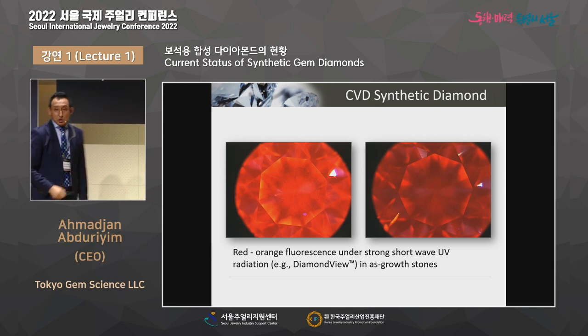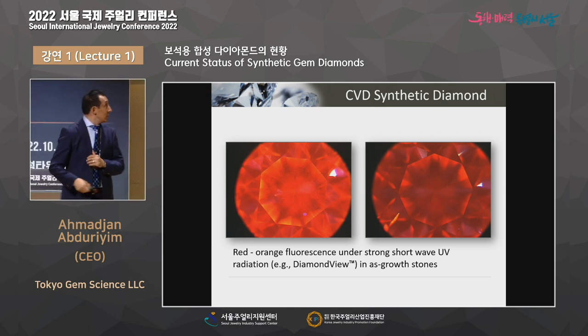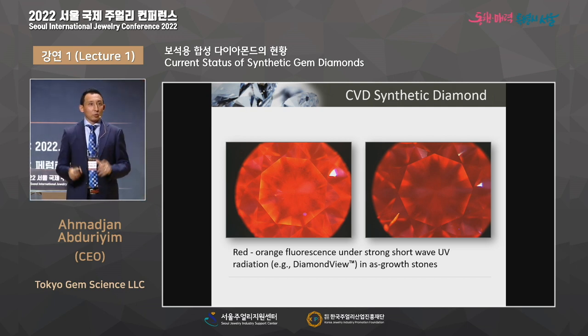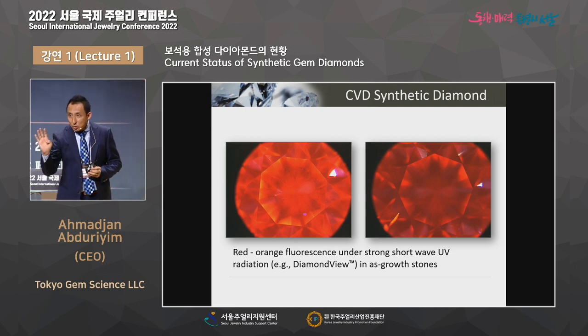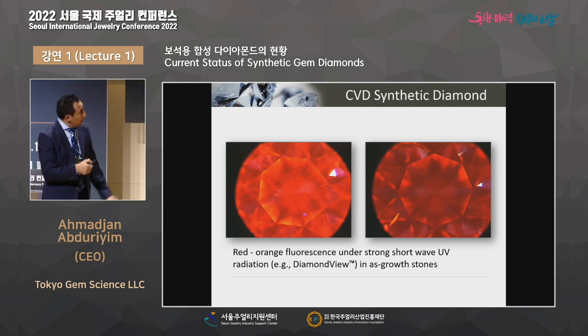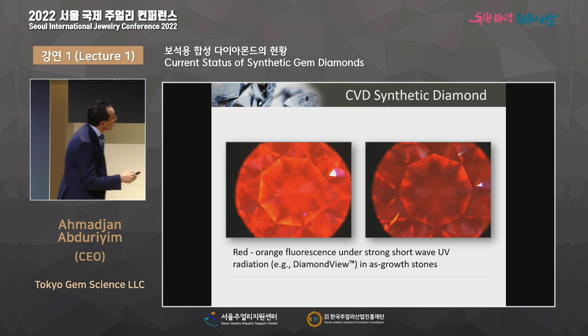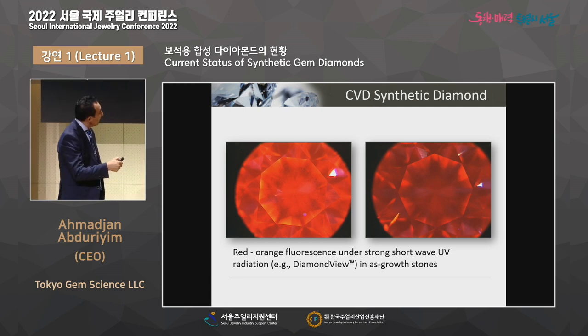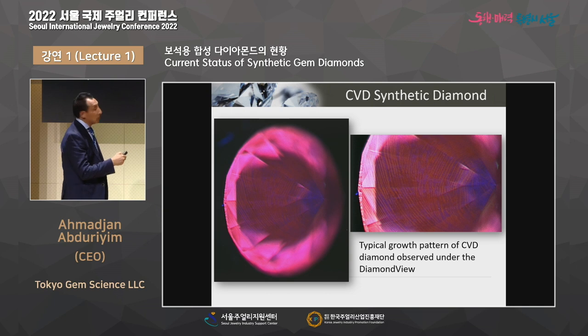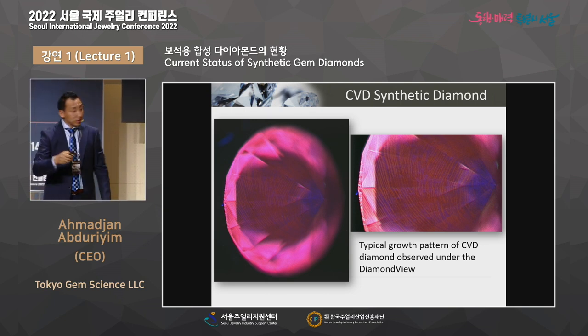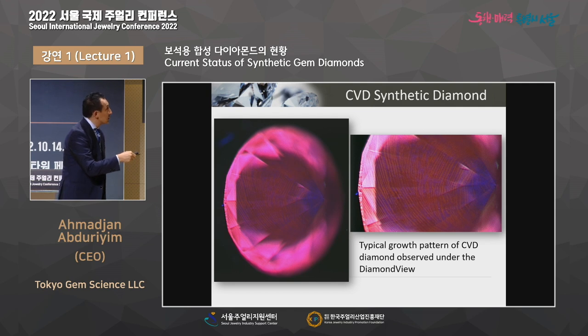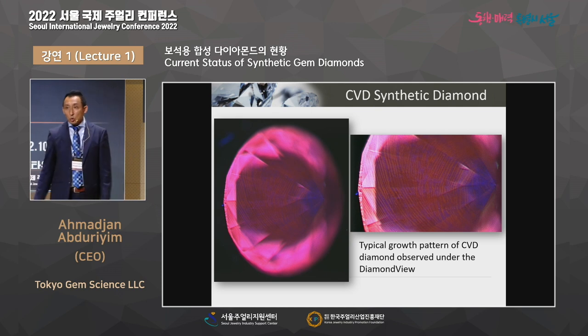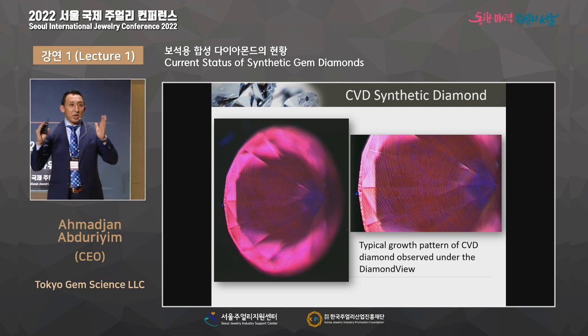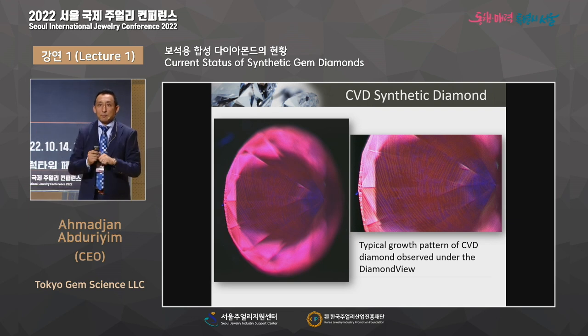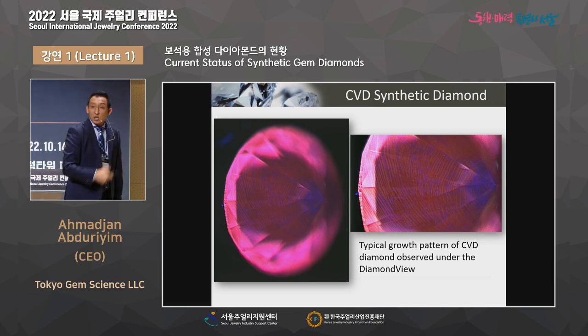You see, they show very strong red fluorescence. You never see such strong red fluorescence; Argyle pink diamonds show a little bit weaker than this. And here we try to see the very tiny growth structure. It's difficult to see. From the side view, you see layer by layer. This is definitely a CVD diamond. You never see this structure in natural diamond. You never see this structure in HPHT synthetic diamond. The growth sectors and environment are different. So this one helps you.